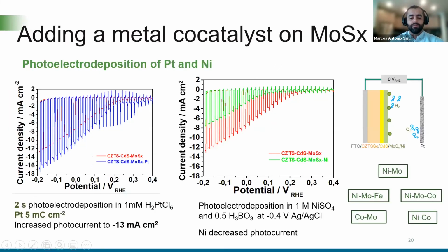We also investigated the effect of an additional metallic catalyst after the molybdenum sulfide deposition. We deposited a very small amount of platinum. You can see that we used only a charge of 5 millicoulombs in a 2 second deposition. Here I'm showing the results for platinum as a control to compare with all the metals, and we reached a photocurrent of 13 milliampere per square centimeter. The nickel didn't act as a good co-catalyst for water splitting, but here we use it as a proof of concept to soon evaluate other metal alloys with nickel, which are very well known as good electrocatalysts for the hydrogen evolution reaction.